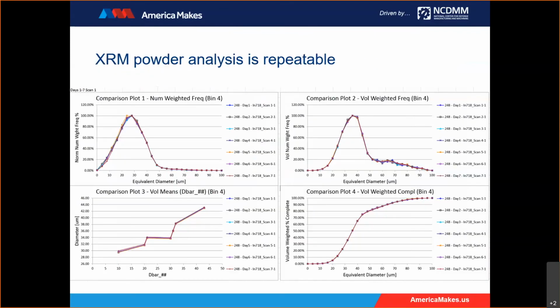Here you can see some number and volume weighted frequency and cumulative plots of the same powder imaged over 7 days at different points along the capillary tube. And we can see that we have very consistent results. The D values are very consistent over this time. So XRM is a great technique for powder characterization.